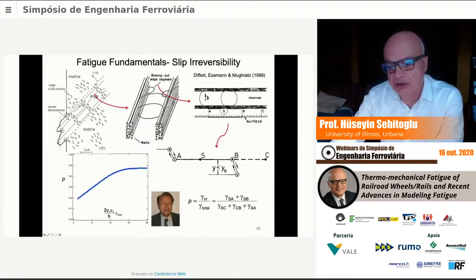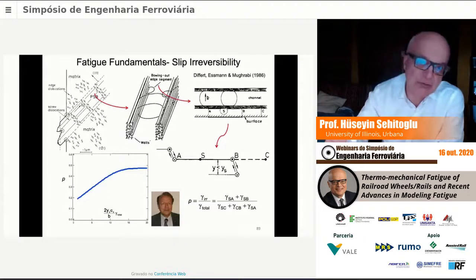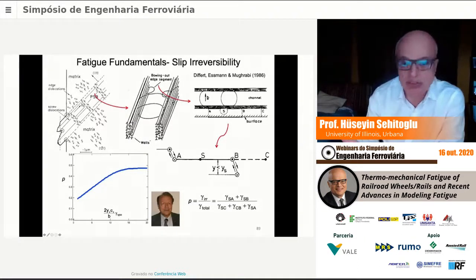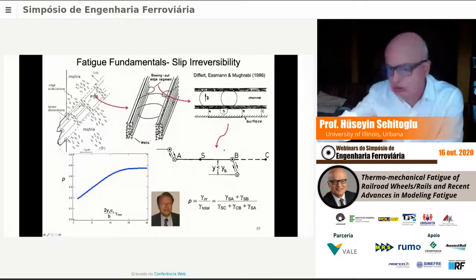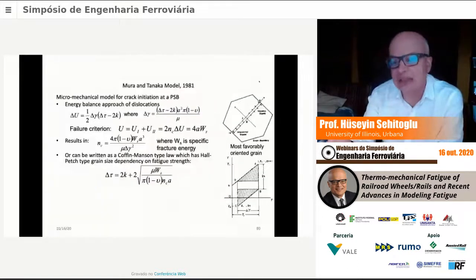So in this simple path, the irreversible part is clearly SA and SB, okay? That's the part that didn't return. The total path is SC, CB, and then SA. So that's an irreversibility parameter. And we can determine that with modeling, right? If the irreversibility was zero, we wouldn't have fatigue because the dislocation comes back, but it doesn't come back fully, and we get irreversibility. This irreversibility is a function of gamma.